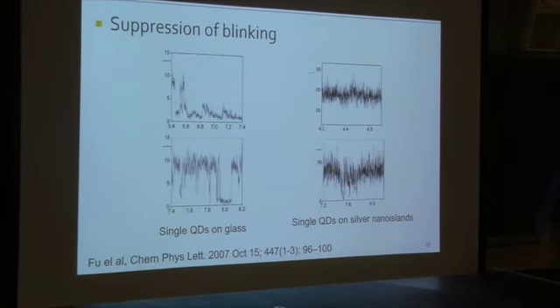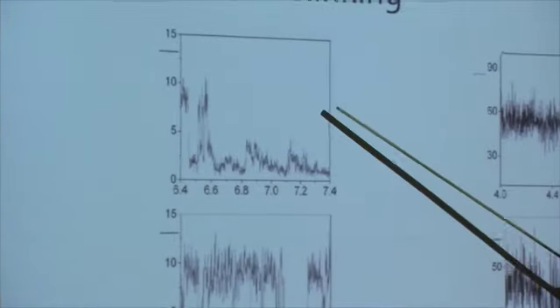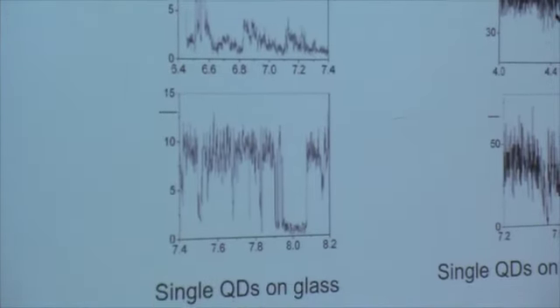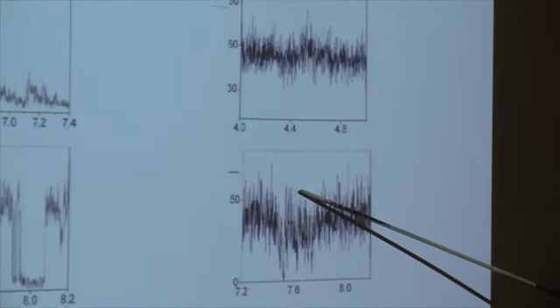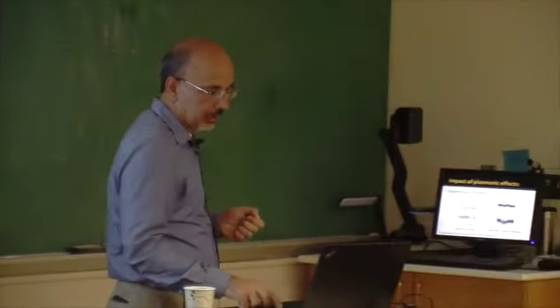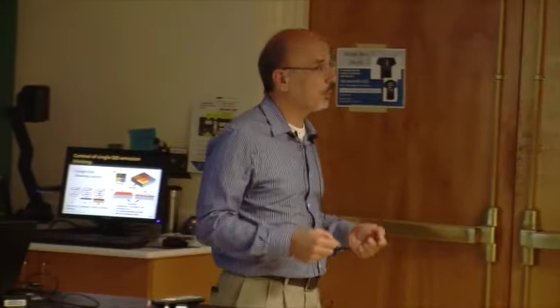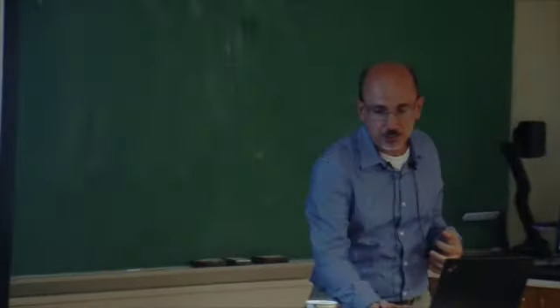close to a metallic nanoparticle. So this is blinking in the absence of metallic nanoparticles, and this is blinking in the presence of metallic nanoparticles. So the common idea is that metallic nanoparticles suppress blinking. The reason is that field enhancement enhances radiative decay. Radiative decay can become so competitive with the Auger recombination that it doesn't allow Auger recombination to happen so much. So that's the reason it reduces, and you have less. This is the idea behind having a metallic nanoparticle reducing the blinking.